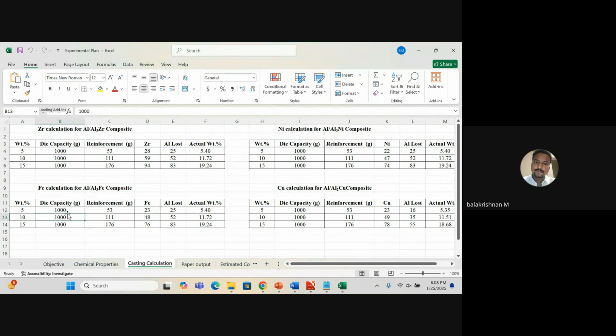Suppose I'm changing the die capacity to 2 kg, that is 2000 grams. Automatically the reinforcement calculations change. So actual volume percentage we can get. Suppose we are considering for 15 weight percentage, so I have to add 353 grams of ferrous. This calculation is calculated with the help of literature and some other reference material.